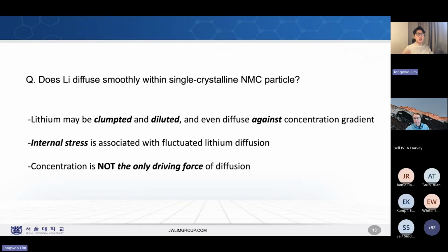So this is one of the curveballs that the batteries throw at you, because in 99% of the papers, we always assume lithium concentration is the major driving force of the diffusion. Yes, maybe it's one of the major driving forces, but we have to consider strain and stress information at the same time, because they also drive the lithium concentration too. So this is the first part.